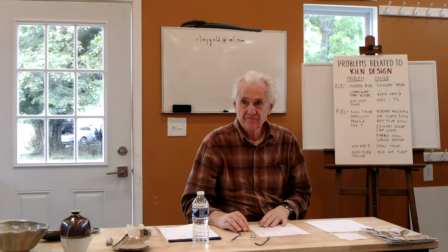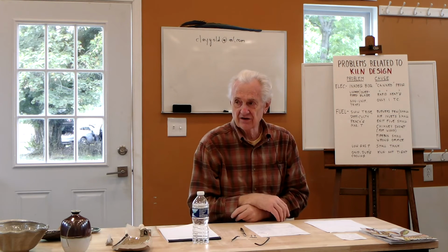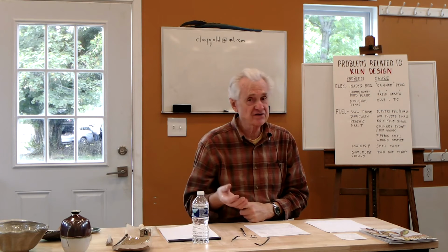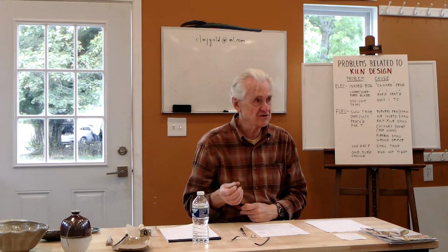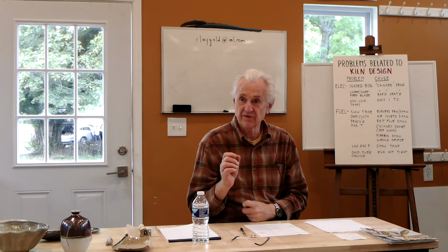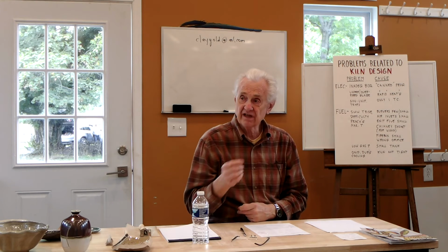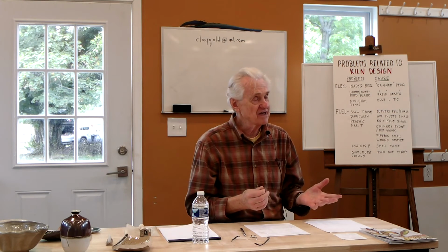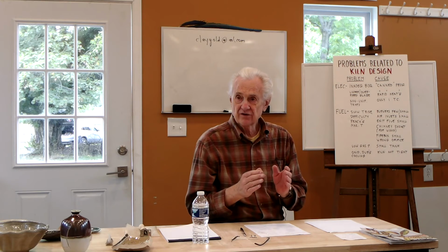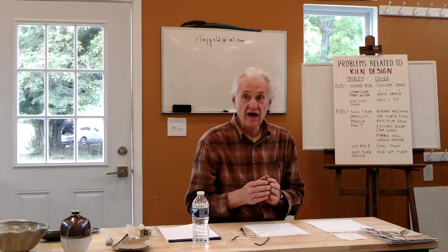And just 20 degrees? 20 degrees is enough on a lot of glazes. This is especially true, I've found, with commercial glazes. Commercial glazes tend to be more temperature sensitive because of the way they're formulated than some of the glazes you can make up. If you make up the glazes from your own materials, you can formulate glazes that have a pretty wide temperature range.